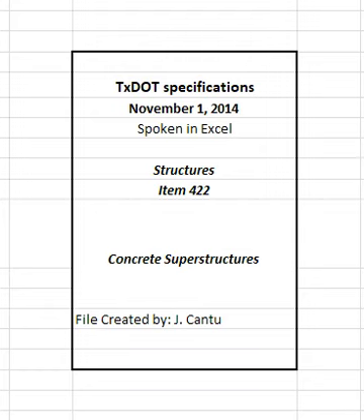Deposit slab concrete between the exterior beam and the adjacent beam before placing concrete in the overhang portion of the slab. Place concrete in longitudinal strips starting at a point in the center of the segment adjacent to one side except as the section indicates, and complete the strip by placing uniformly in both directions toward the ends. Start placing at the lowest end for spans on a profile grade of 1.5% or more. Use strips wide enough that the concrete within each strip remains plastic until placement of the adjacent strip. Place the concrete in proper sequence to be monolithic with the adjacent longitudinal strips of the slabs where monolithic curb construction is specified.